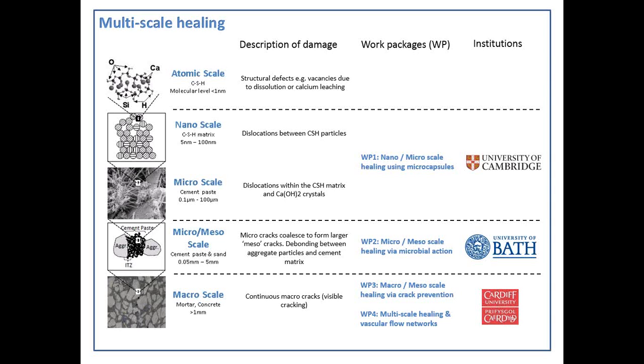The concept behind this is that macro scale or visible cracks don't just appear as they are, they develop over time from micro cracks which form due to those damage scenarios I mentioned earlier, until they become large enough to cause a problem. So they allow the ingress of water, salts, chlorides, etc. into the concrete matrix, which then causes a problem. It causes damage, and this is when you require repair to your structures, when you have spalling of your concrete, and you have corrosion of your reinforcement, etc.